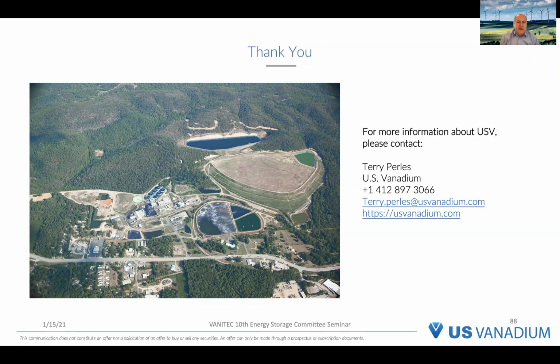What are the main vanadium sources? Is mining still the most economical way to get pure vanadium, or are other process methods coming to market? So today, about 70% of the vanadium is produced from slags, vanadium-bearing slags generated by steel mills in Hebei and Sichuan provinces in China and in the Ural Mountain region of Russia, as well as one very small mill in New Zealand. All of these mills process a vanadium-bearing magnetite to make steel. And in the steel making process, they'll drive the vanadium into the slag. They'll generate a slag that's anywhere from 14 to 24% V2O5 content. And that is the source of the majority of the world's vanadium production today.